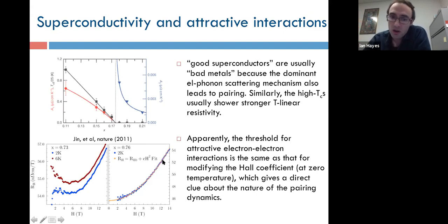Whereas in the Hall coefficient here, we see a temperature evolution of the behavior. We see some zero temperature part where the correction of the Hall coefficient seems to be exactly related to whatever attractive part of the interaction there is. And then you see some thermal evolution such that even non-superconducting samples can exhibit this behavior on the overdoped side. So there's quite likely even more information present in the temperature dependence of the Hall coefficient here, once you've been able to factor out everything with the field.